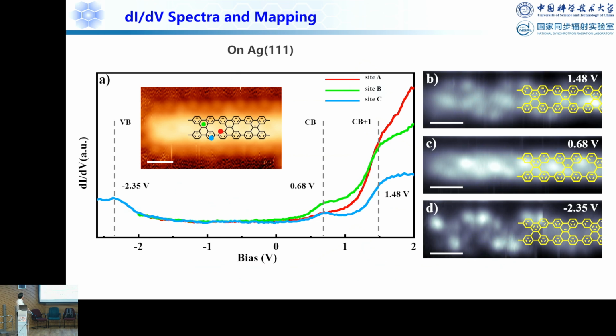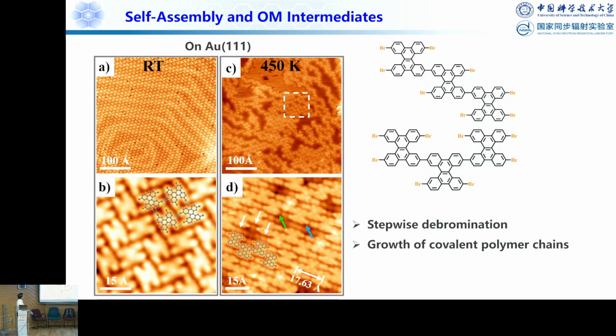And then we characterize the electronic structure by measuring the dI/dV mapping. This is in collaboration with my former student Qitang, because in my group I don't have the low temperature STM facility. So here you can see the band gap around 3.0 eV, and if you do this dI/dV mapping at this bias, you can see the local density of states along this ring. So this is the ring.